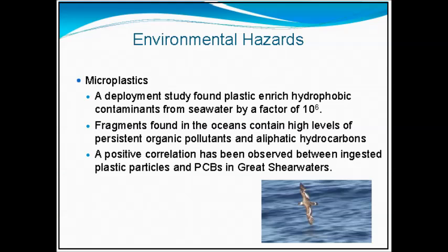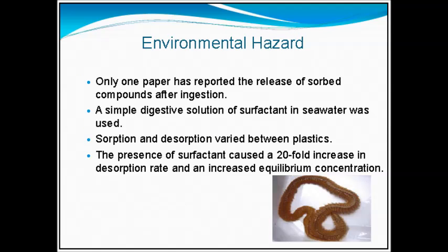So microplastics, a deployed study found plastics enrich, this is one of the problems, what are the environmental hazards associated with all this stuff? Well, it turns out that these microplastics are enriched in hydrophobic contaminants. In other words, anything that's organic, non-polar will assimilate in these types. So they're collecting these materials and seeing where they can increase the concentration by 10 to the 6, for example. So small particles could have a reasonable concentration of these contaminants as well. Contaminants like chlorinated hydrocarbons, aliphatic, other aliphatic structures, and so forth. There has only been one study where they've actually shown a correlation between ingested plastic particles and PCBs, and that's with great shearwaters, excuse me. So there has been very little done in terms of evaluating the impacts from the point of view of the chemical contaminants being carried.